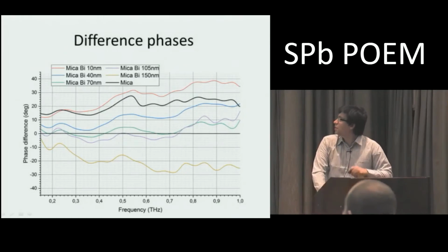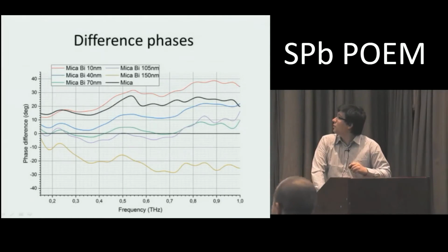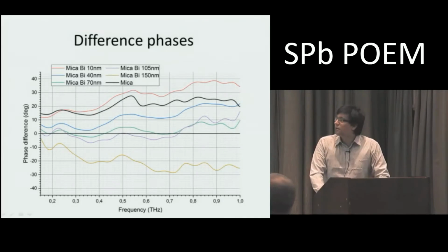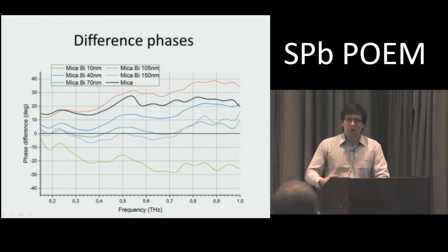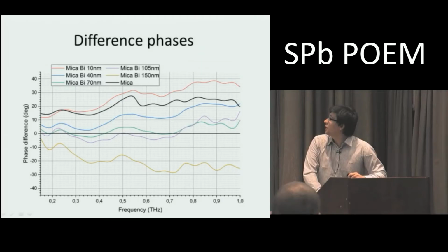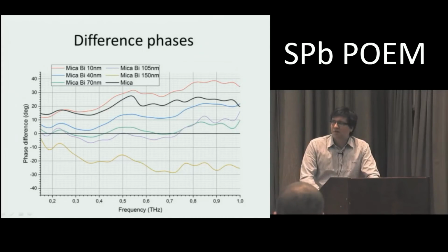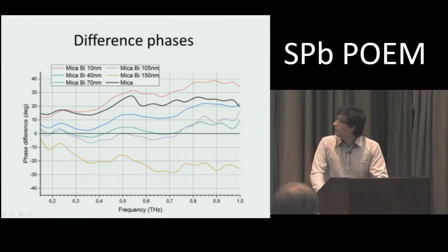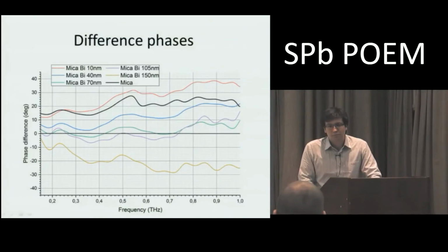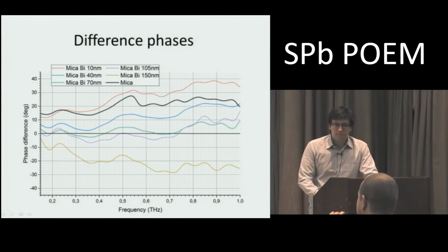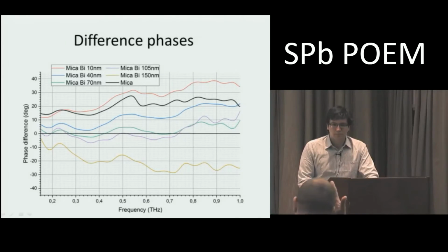I think yes, because for 150 nanometer, the nanolayer becomes like a bulk material. From 10 to 40 nanometers we can see some quantum effects, and from 40 to 100. But did you see any other reports in literature of this effect of negative permittivity in bulk bismuth? Did you check the overall literature? I can't remember. I have seen some papers on use of bismuth for terahertz applications, but I can't remember any results reporting negative permittivity.